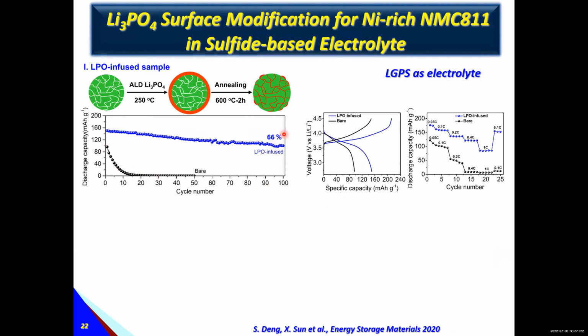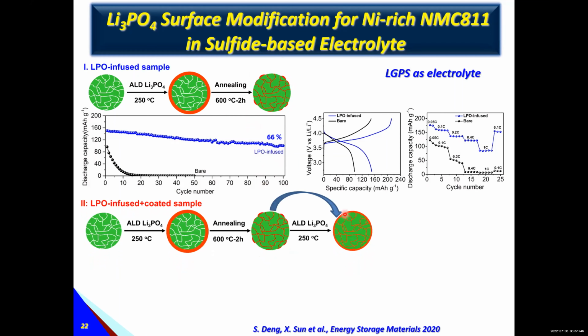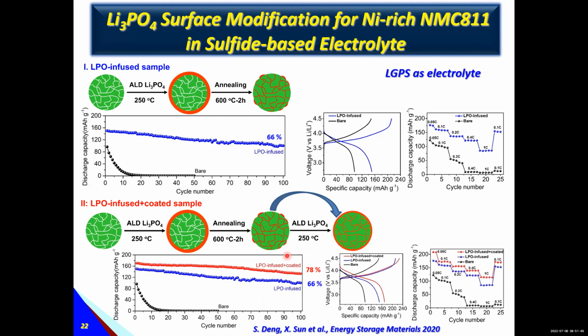It's from 92% retention after 200 cycles, now it's 66% after 100 cycles. So that means the bigger challenge is solid state electrolyte. So we can see this part actually with the sulfide-based, after annealing the material penetrates inside, but the coating here is not continuous on the surface. So we try to see if I have an extra coating on top, can we improve performance? Actually, yes. After we have additional coating on the top, we can increase to 78%. Rate capability is better too. But still have a challenge.